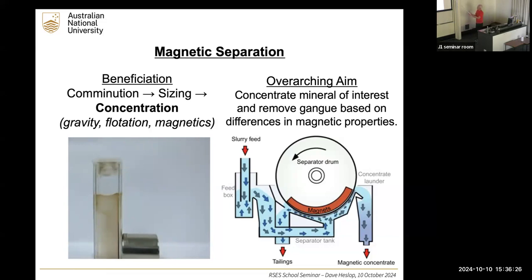So the overarching aim is to concentrate your mineral of interest, in this case an iron-bearing mineral, and remove the gangue based on differences in magnetic property. This is a cartoon of what's called a LIMS, a low-intensity magnetic separator. The iron ore is fed in as a slurry here and flushed through the system. Then we have a set of magnets that are fixed in position, but around those magnets there is a rotating drum.